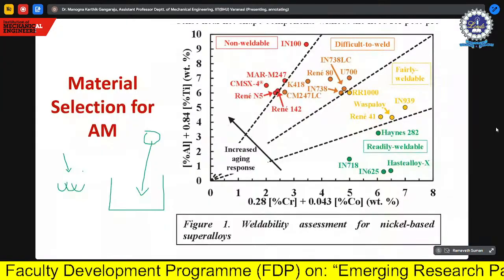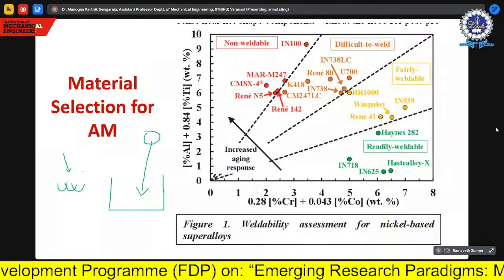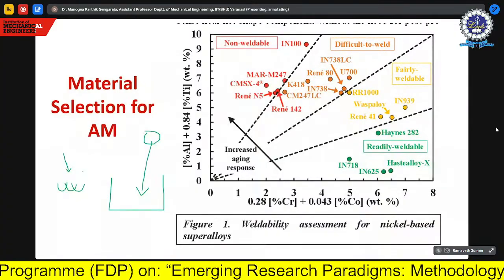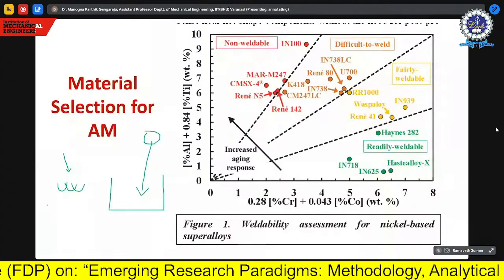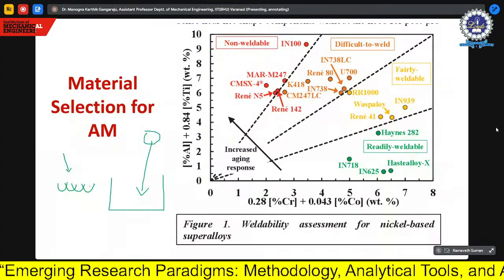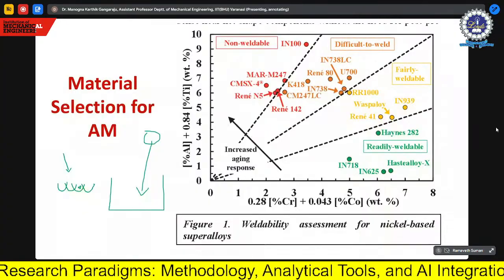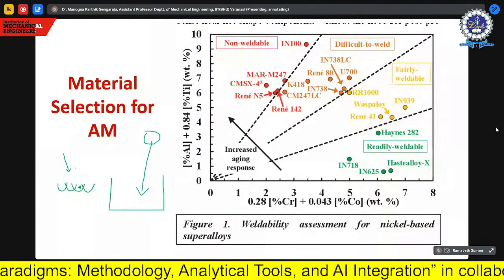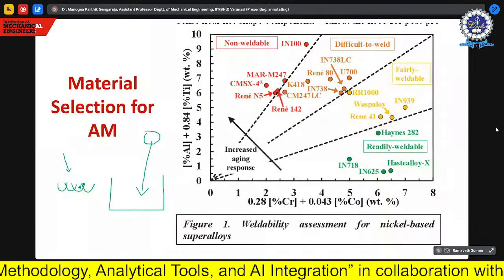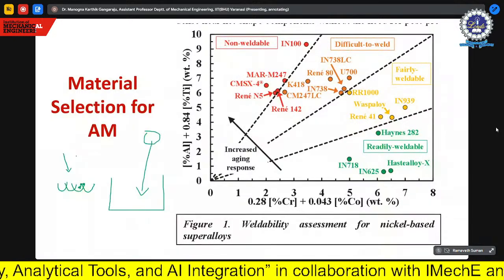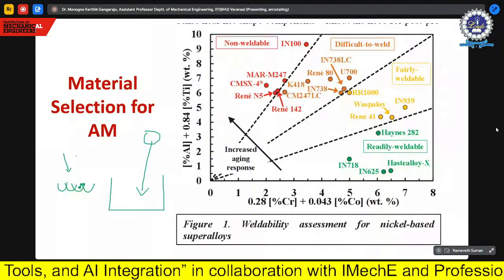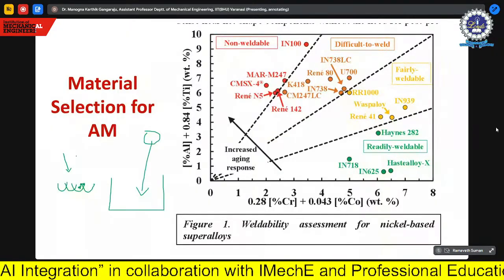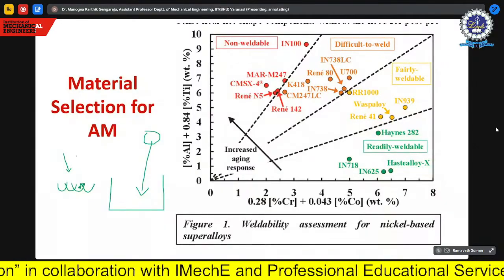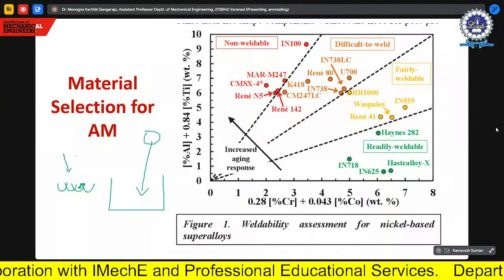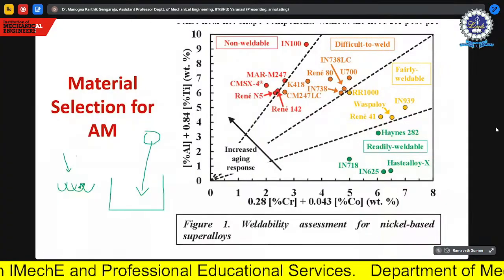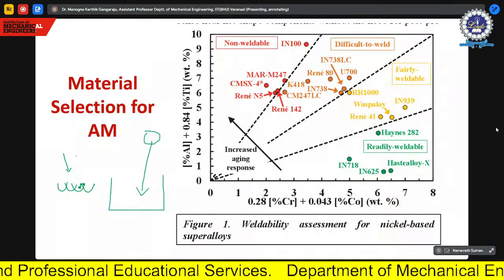In the case of additive manufacturing, the material is not experiencing heat at the same time. The material is experiencing heating, cooling, reheating. When you are depositing this particular layer track, you are reheating this particular track. So there are multiple remelting, and this region is remelted again. So you have several remelting, several reheating, and the material is also locally melted and solidified. Because of that, you have several issues like cracking. Some materials are very difficult to process, and those will be very difficult for additive manufacturing.